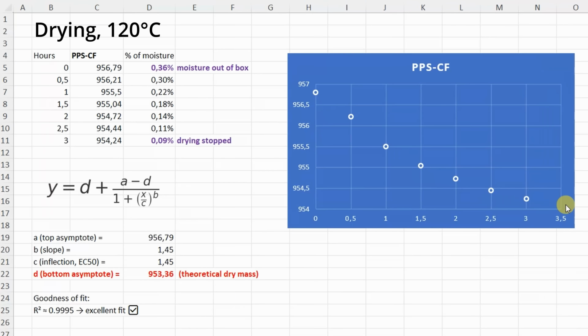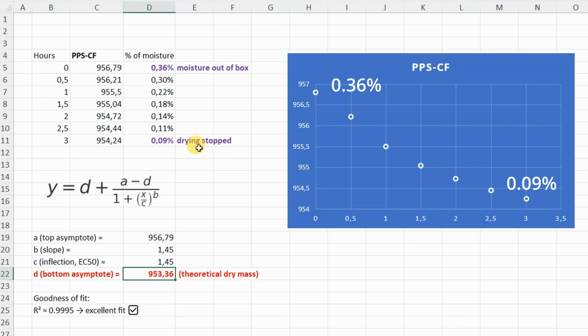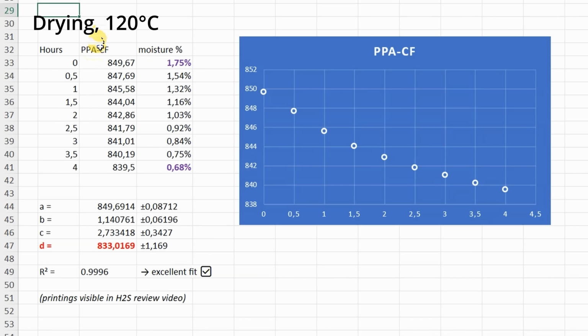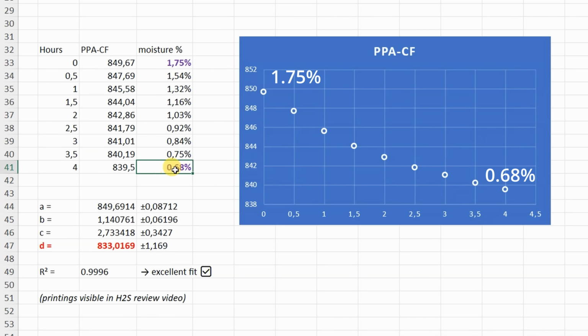These are the measure points, and in infinity it will become a constant, and that can be calculated. And there's a theoretical dry mass, and from this I calculated that I stopped the drying at 0.09% of the moisture, but even out of the box with 0.36 it will be completely fine. Same calculation for PPA-CF, it started from 1.75 and ended with 0.68% of the moisture after 4 hours of drying. You can see the printings in my H2S review video.